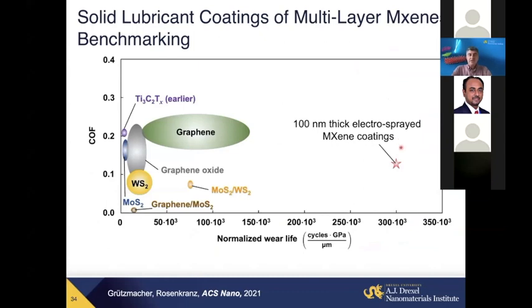And actually, this was really an amazing result obtained in normalized wear life, greatly outperforming all other materials, including earlier tested titanium carbide MXenes here, in, first of all, wear life here, with also quite a low friction coefficient for this material here. So it basically means that MXene can outperform solid lubricants here.